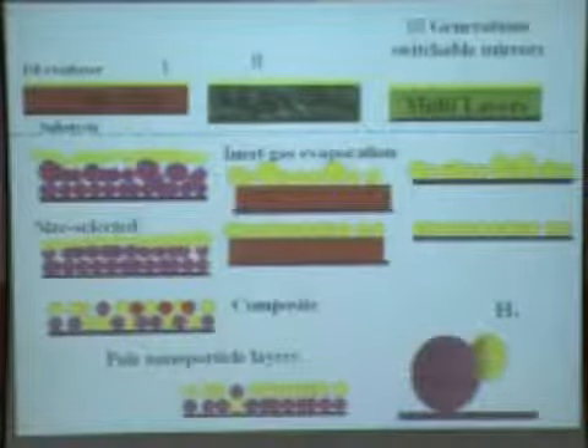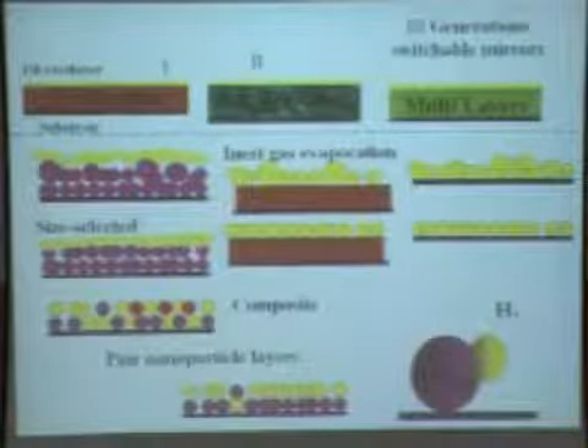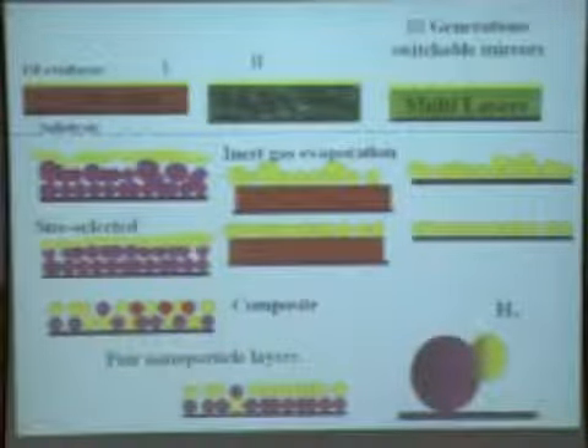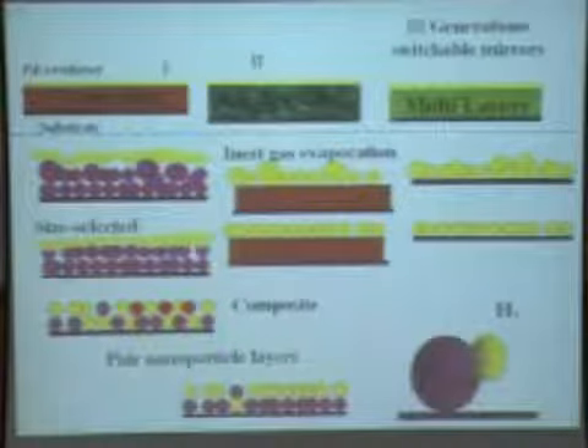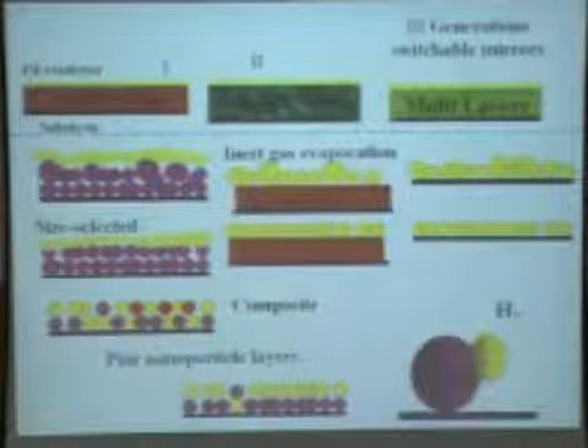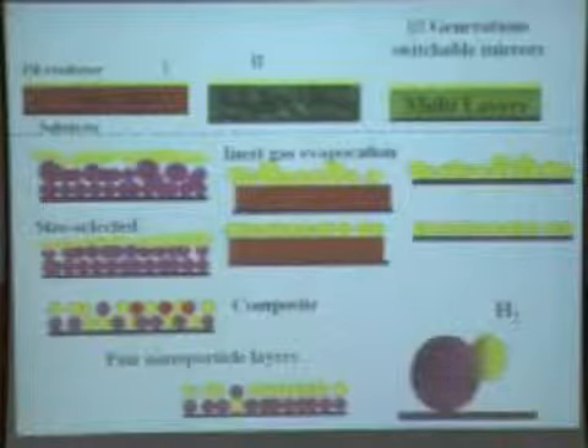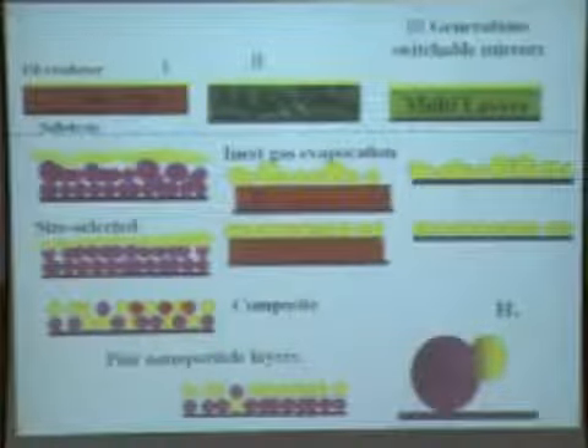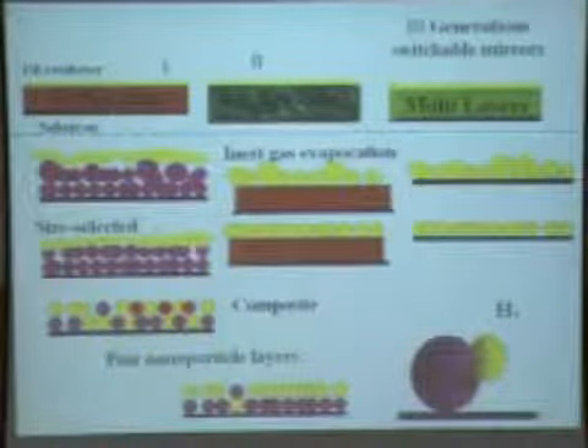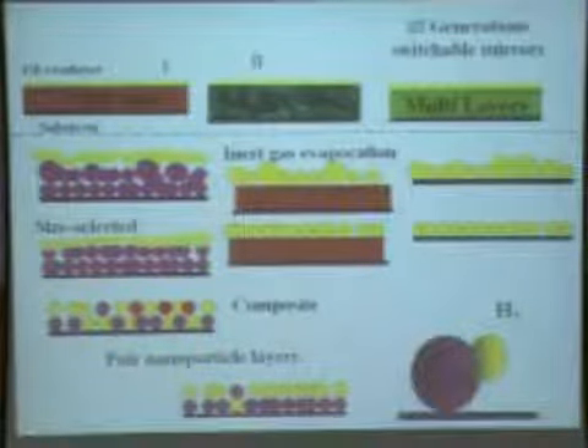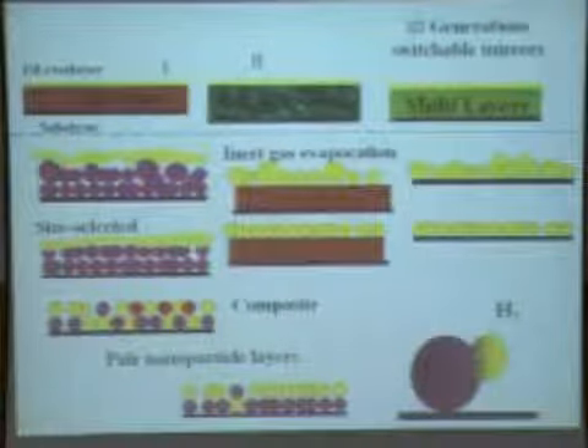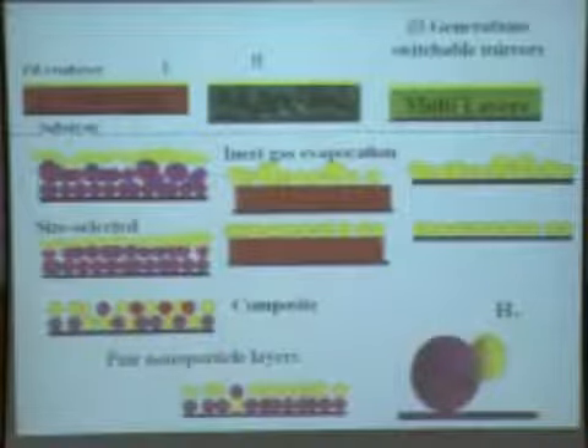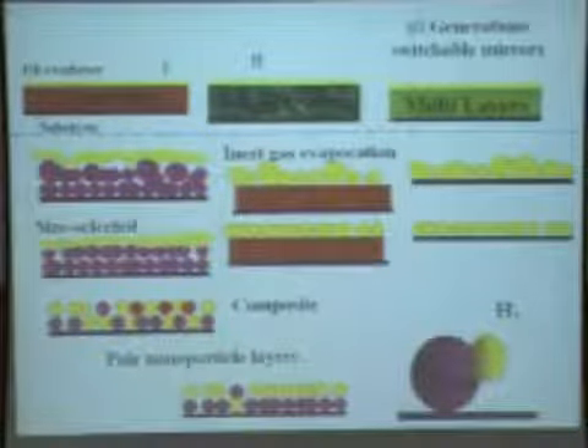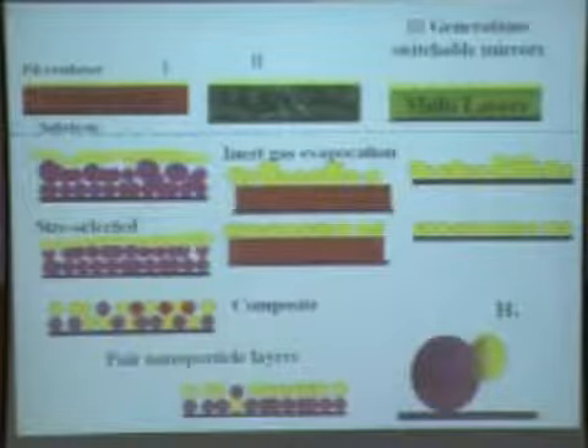When we have a film of nanoparticles, the hysteresis comes out because of the interaction between the particles. Because you have one particle and there are other particles present along the way, they do not allow the particle to expand and contract. That is one of the reasons for hysteresis. If you have an independent particle interacting with hydrogen and you can measure its electrical properties, it should be possible in a single particle or pair nanoparticle, single nanoparticle space. That is our present research goal.